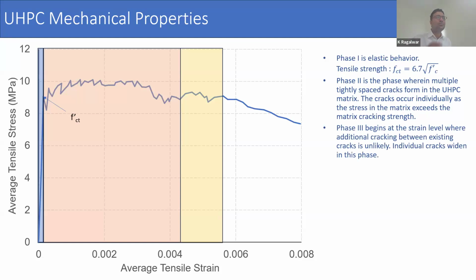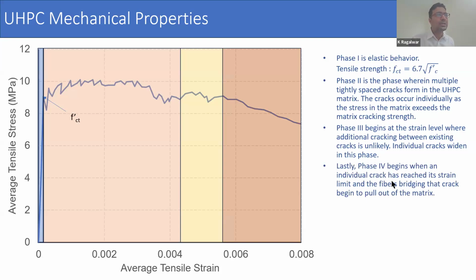start widening. So there are no more new cracks. At this point, we have probably exhausted the fiber bridging capacity, and now we are seeing what is known as localization of crack. So phase 4 would be where one individual crack completely opens up, and then you would see that fibers are completely pulled out at the crack, unable to bridge it, and the crack keeps opening, and the neutral axis kind of keeps going up. Basically we see almost sort of a hinge formed, or not a hinge in this case, but we see complete pull out of fiber. So this is uniaxial tensile.